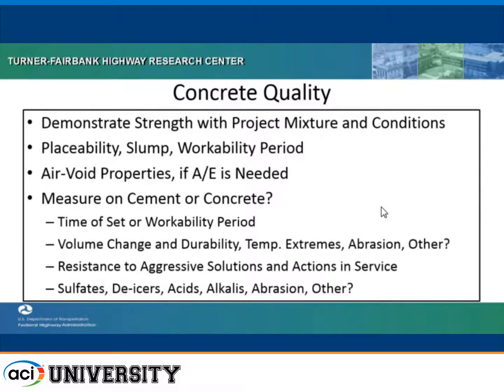On the concrete quality, we need to demonstrate for the particular project with a mixture that is going to be used, that you're going to get strength. Can you pump this material and place it if necessary? Air void properties. So far, most of what we're looking at, we're using air entrainment. Now, there may be some alternative cements that will have sufficient durability without needing air entrainment. That would need to be a factor to be considered.